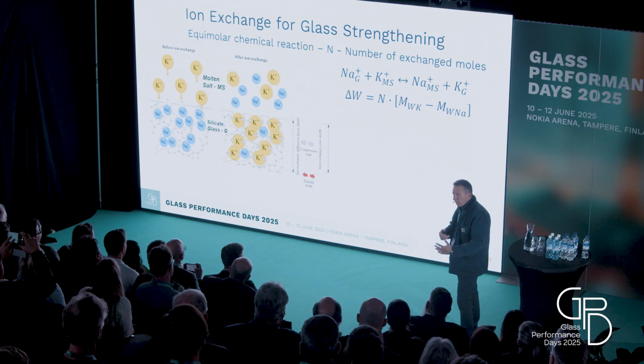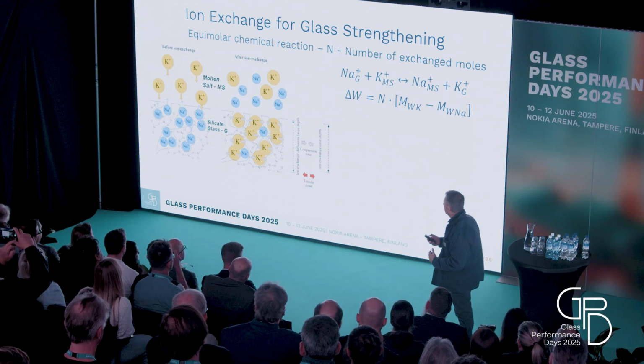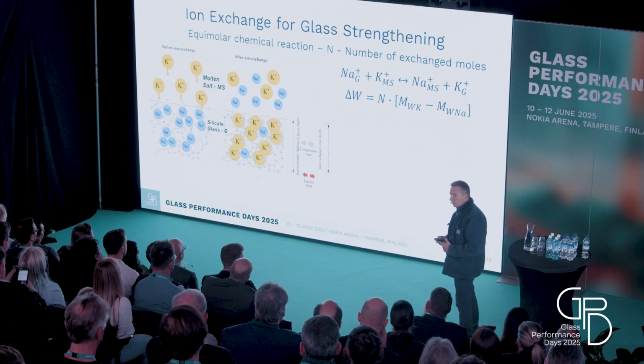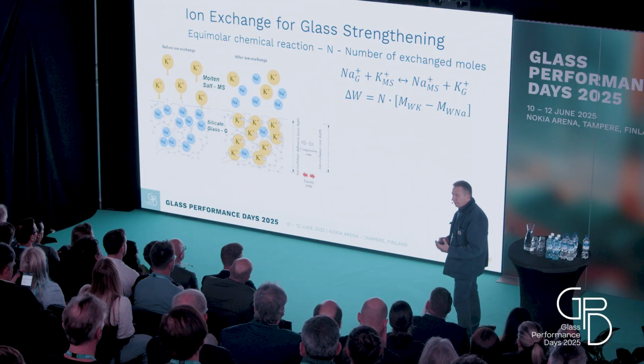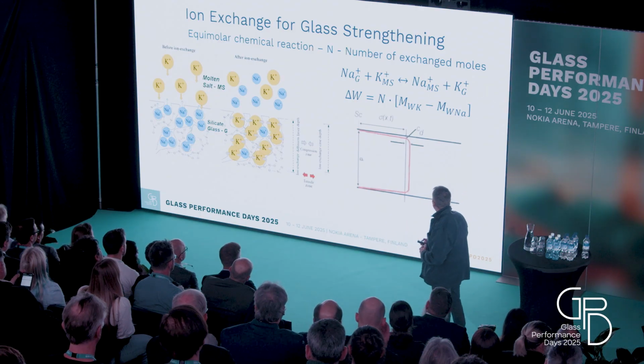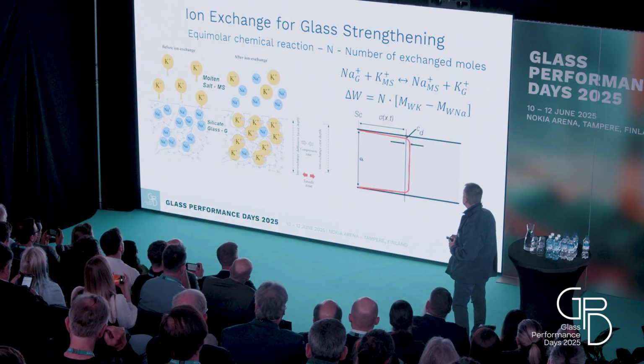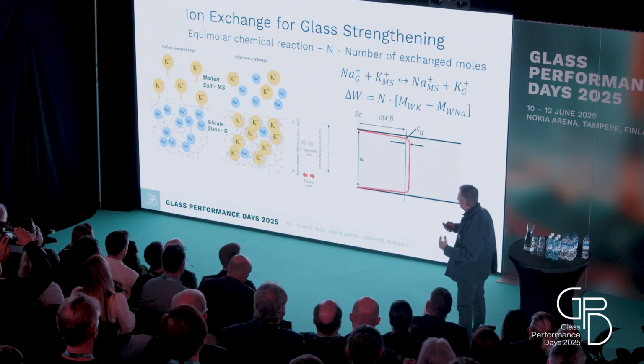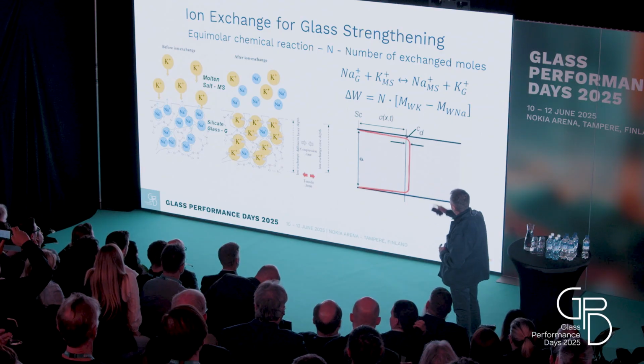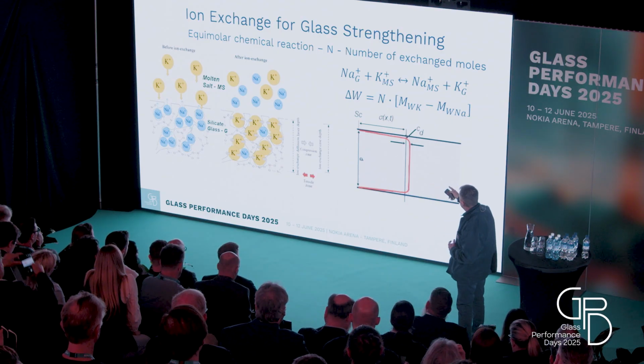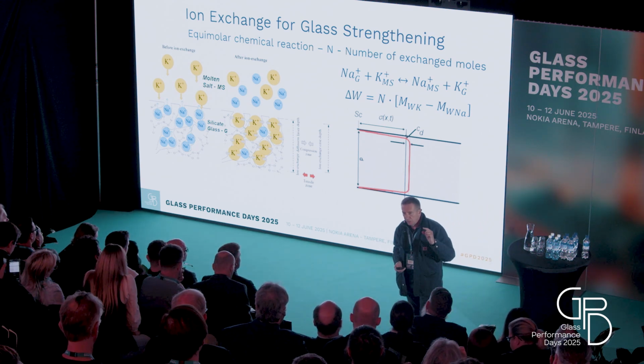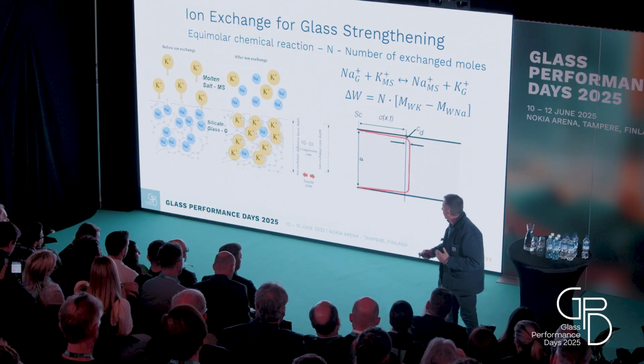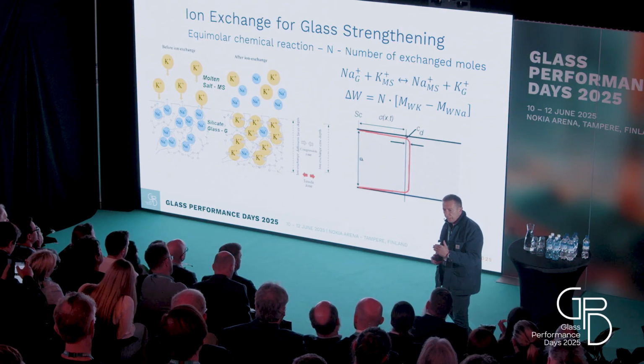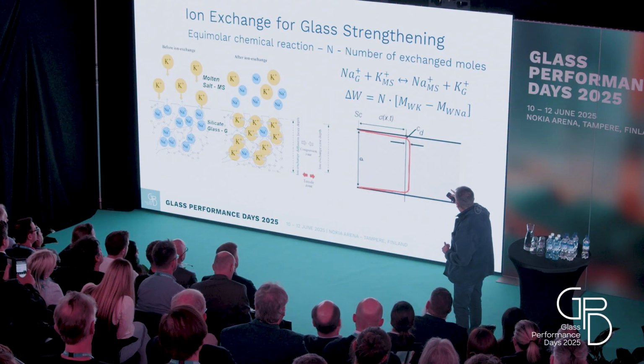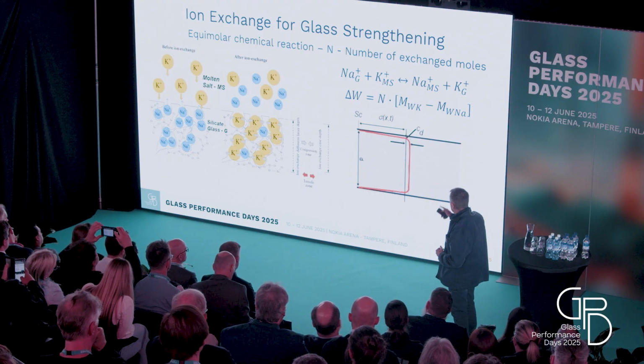And if you multiply the number of moles that has been exchanged in the glass by the difference in the molecular weight of the two species, then you have a weight increase in the glass. We will use this equation later on. And this is, again, a schematic representation of the stresses generated in this process. So you have a surface compression, SC. You have a depth of compression, which is the distance between the surface of the glass and the point where the stress changes from compression to tensile, so when the stress is zero. And the other element is the central tension, which is obviously the remaining part at the center of the glass.